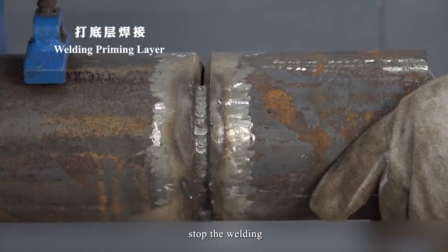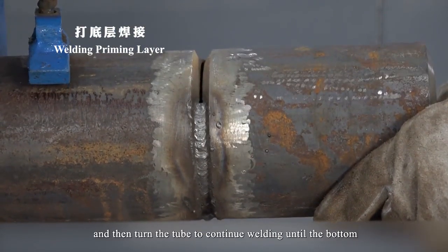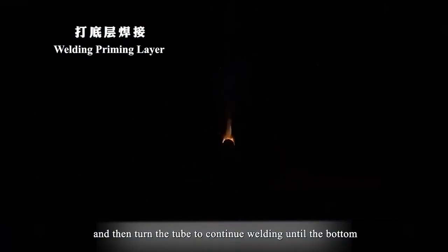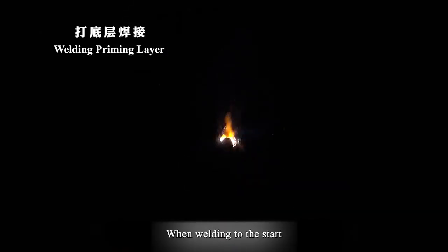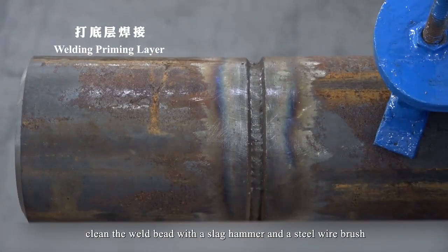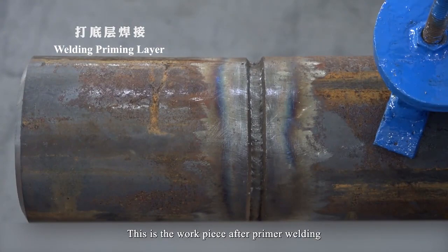When the welding reaches the 12 o'clock direction, stop the welding. Then turn the tube to continue welding until the bottom welding joint is complete. When welding to the start, continue to weld forward for 3 to 5 mm to ensure the full fusion of the joint position and the quality of the joint. After welding the primer, clean the weld bead with a slag hammer and a steel wire brush. This is a workpiece after primer welding.